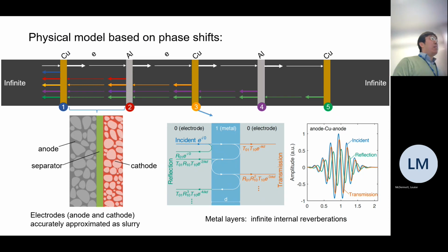And resonances are essentially phase shifted waves, and their phase differences need to be 2 pi apart. So we need to investigate how the phase shifts are happening inside of these layers as well as the electrodes. So the first interesting finding